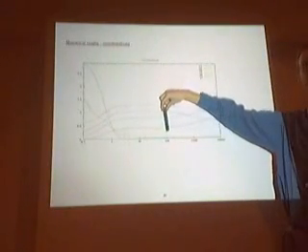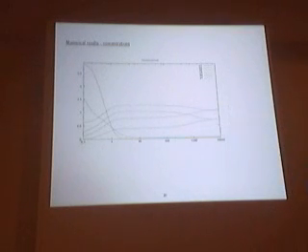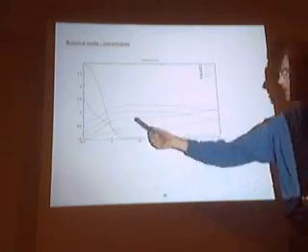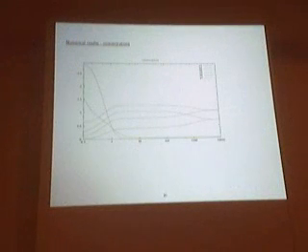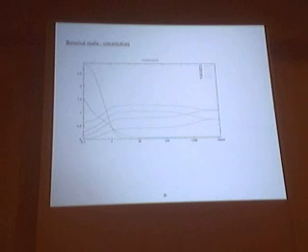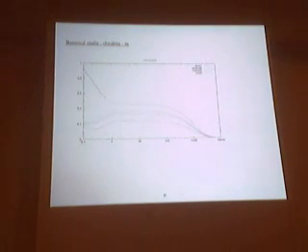So this is a log scale. You can run it for 10, and it looks like it's reached steady state. You run it for 100, and it still looks like it's reached steady state. But you run it for 1,000 or 10,000, and eventually it becomes racemic. So this is 2 or 3 orders of magnitude that it stays symmetry broken, but it's not really at steady state. It's going to become racemic. So it looks like we're really close, and you can try changing the parameter values and looking again, and it does the same thing over and over again.